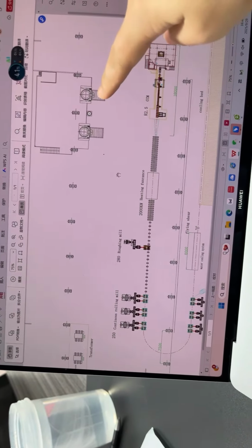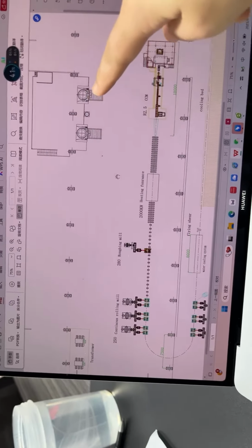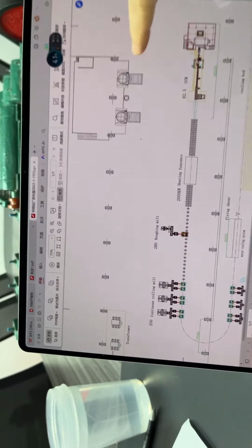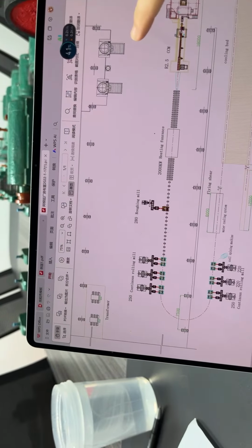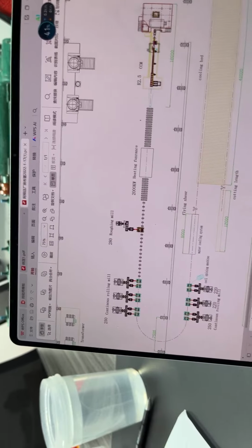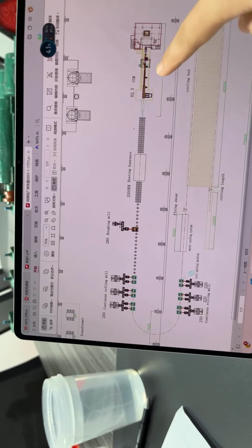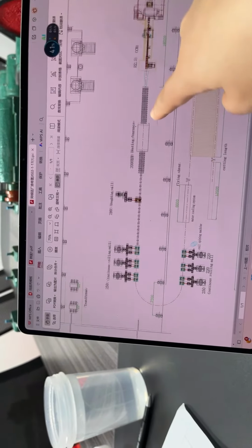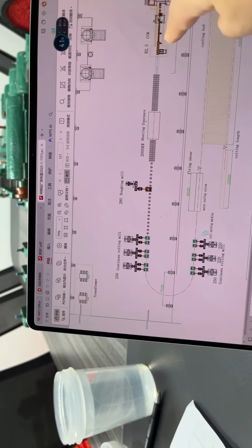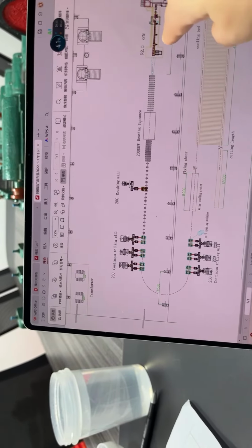Here we can see the melting furnace. This one is the bigger one. The furnace capacity is around 10 ton. And after the 10 ton melting furnace melts the steel into liquid, here we have the CCM pouring the liquid into the tundish and then casting the billet out. The billet coming out from the CCM is around 700 to 900 degrees.